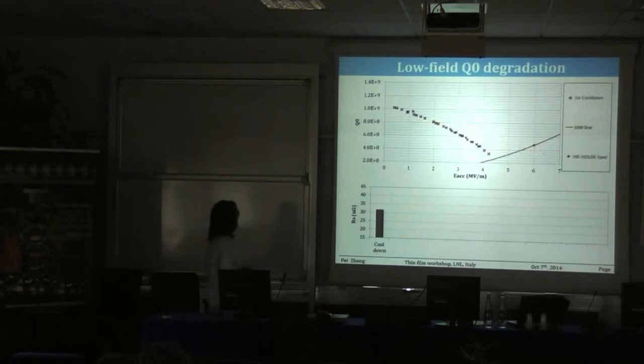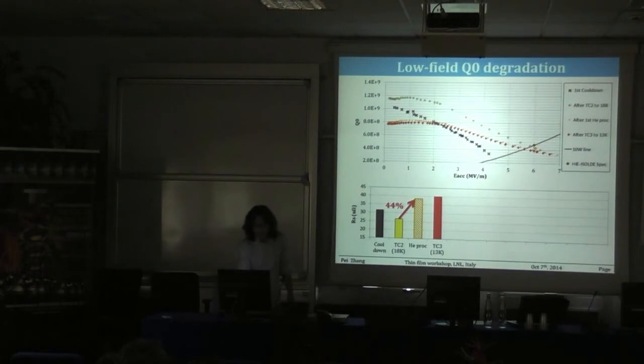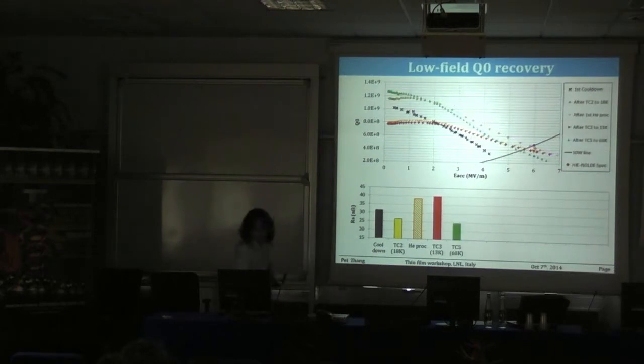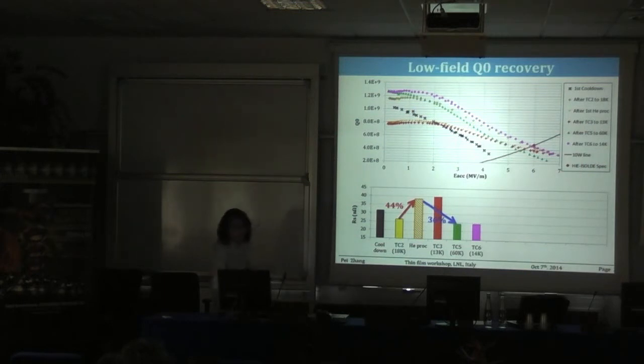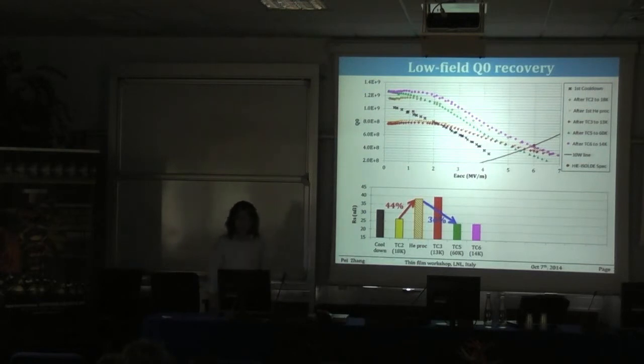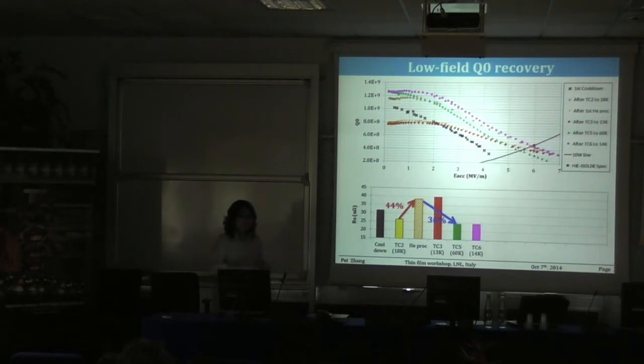In the most recent tests, we tested another cavity that showed field emission. After helium processing, we see significant degradation of the low-field Q0 — about 45% — and this cannot be recovered by a normal thermocycle up to 13K. However, if you warm up to 60K instead of 13K, you can recover the low-field Q0. Our suspicion is that after helium processing, some gas is adsorbed onto the surface, and you need to warm up higher to release and remove it.